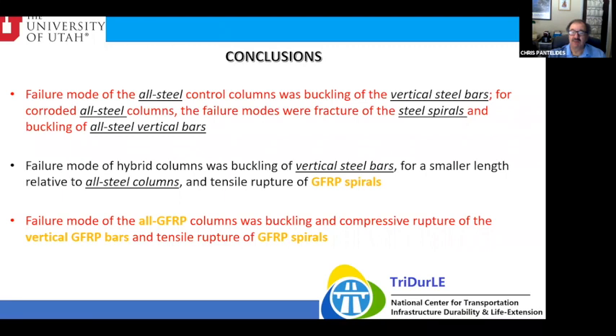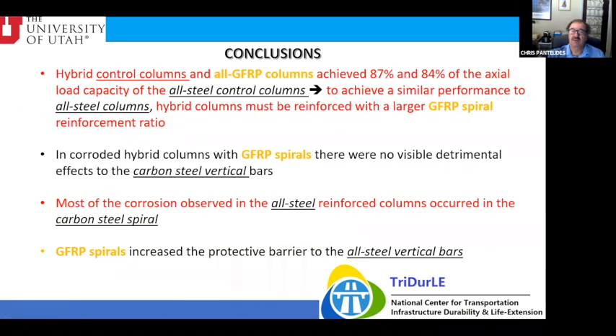Failure mode of hybrid columns was buckling of the vertical steel bars, but for a smaller length relative to the all steel columns, and tensile rupture of the fiberglass spirals. Failure mode of the all fiberglass columns was buckling and compressive rupture of the vertical GFRP bars and tensile rupture of the GFRP spirals. The hybrid control columns and the all GFRP columns achieved about 87 to 84% of the axial load capacity of the all steel control columns.